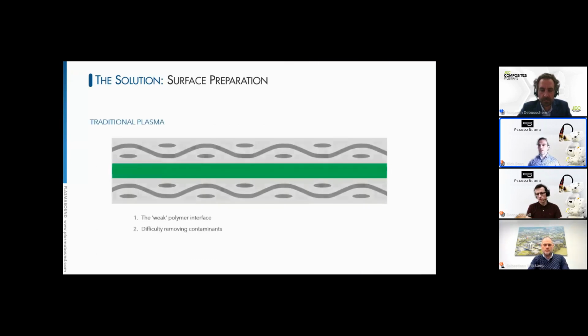So what surface preparation techniques do we use to expand the wettability envelopes traditionally? Well, techniques and approaches such as traditional plasma, roughening, or peel ply have been demonstrated to do this for many decades. Traditional plasma, as illustrated here, does the job really, really well, and it works in many applications. So there are a lot of times where traditional plasma is quite a positive application to use. However, for FRPs, the weak polymer interface remains between the adhesive and the fiber structure. It has difficulty also in removing contaminants from the surface, particularly oils. So they will be retained and cause a block to the surface free energy available.